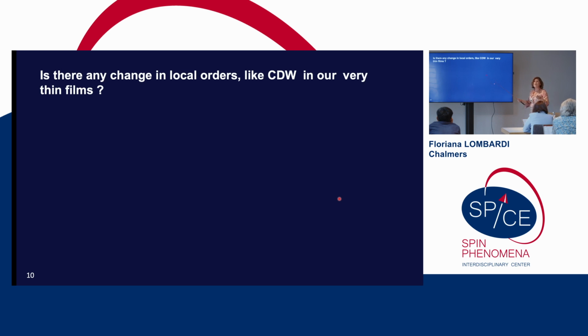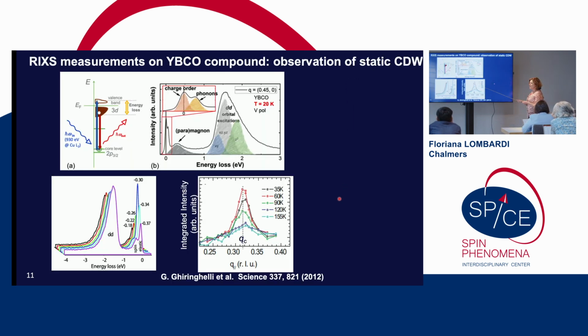Now, what about the rest? We have all these other orders that are playing a role. Does the charge density wave change? And what we did, we took RIXS measurements on these samples. So we took our thin films, went to the synchrotron, and we measured RIXS. RIXS is a technique with a photon in and a photon out, and it is resonant. So you are exciting from the core level of the copper in the copper oxide plane to the valence band. And you can take the intensity of the emitted photon as a function of the energy, and you have the big dd orbital excitation corresponding to this transition. But then at zero energy, you have a peak that is maximum at 0.3. And this peak depends on the temperature. And this has been the first demonstration that charge density wave exists in these materials through RIXS. There were indications with other techniques, like with neutrons from the Ghiringhelli group in Milano.